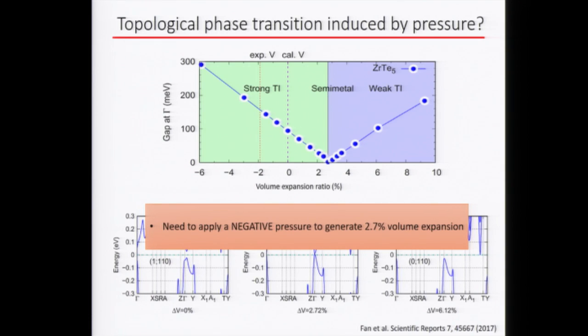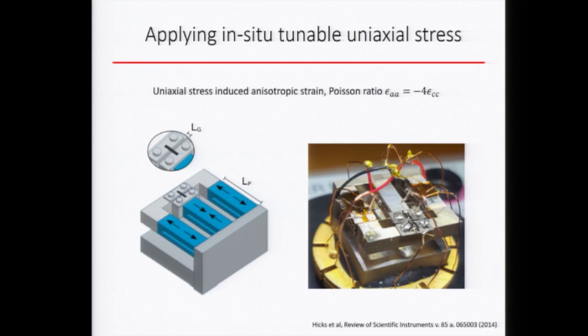But there are ways you can do both positive and negative strain, which is applying a uniaxial strain. That's why we're using this device, which was first introduced by Cliff Hicks et al. The idea is using 3 piezo stacks that amplify the amount of movement of these 2 sample holding stages, and you glue the crystal across this gap. By controlling the motion of this and that independently with these piezo stacks, you can generate strain of the order of 1 to 2%.